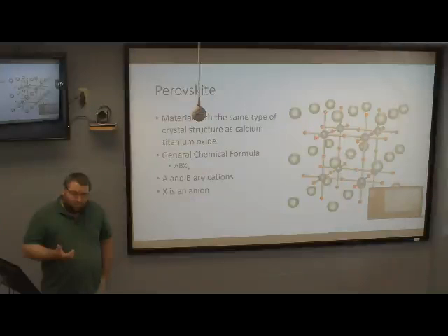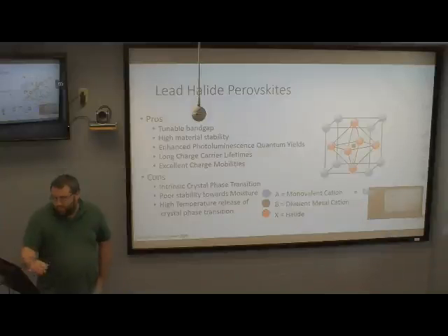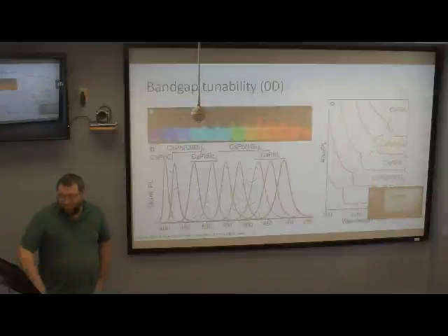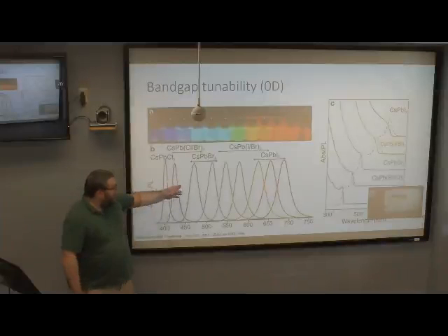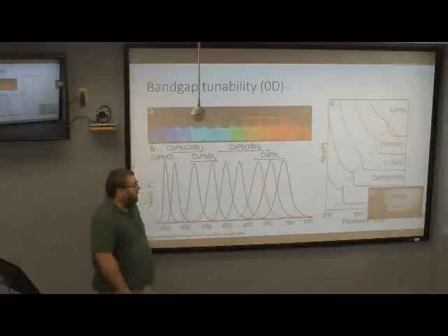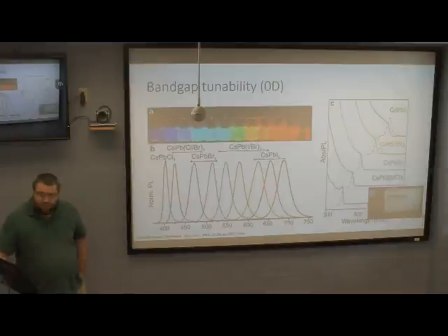In LEDs, it's the tunability that's really what they're looking at, because you can tune it to emit throughout the entire visible spectrum, based on which halide you use and how big the perovskite you make.